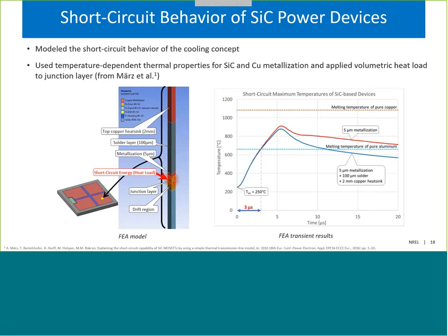And so we developed this one-dimensional transient thermal model that you see on the left. The model is essentially a sliver of a device. It includes all the micrometer layers within the silicon carbide MOSFET. We use temperature-dependent properties for the different layers, and we apply the volumetric heat load at the junction. And so the results are shown on the right-hand side. I'm showing the temperature versus the time response. And note that the time is in microseconds.